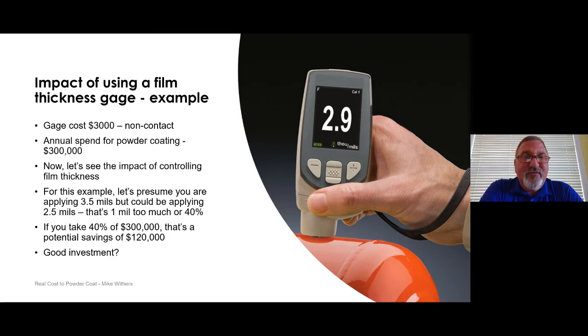The other advantage of using lower film thickness is that as you increase film thickness, especially if you get significantly thicker, you start to negatively impact the mechanical properties of coatings. And so you don't want to do that as well. You don't want parts chipping off as they bang into each other or as they bolt up.